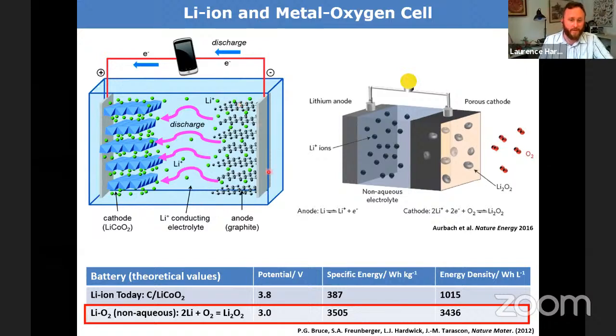We have lithium ions stored within the graphite between the graphene sheets, and as we discharge, an electron is transferred through an external circuit and can be used to do useful work as it then returns back into another layered material, and the lithium is stored between these cobalt oxygen layers. So you can shuttle the lithium ions to and fro in these intercalation reactions, and this is the method for charge storage. Now the lithium oxygen battery works slightly differently, in that some of the components are external. So here we have a sealed system.